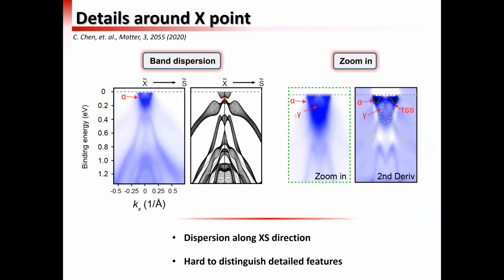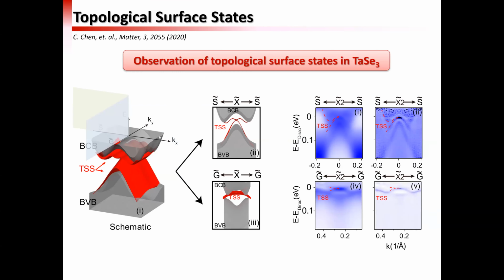If we zoom into that region we just saw before, we were able to see that now, in addition to the blurry bulk conduction and valence bands, there is definitely something in the middle. You can see clearly if we take a derivative of the spectra, and also in this different cutting direction, gamma to X to gamma, there's definitely something in here, and the red broken lines are just a guide to the eye. So there are surface states living inside the bulk gap of the conduction and valence bands of the tantalum triselenide, and so we confirm that this material does have a topological electronic structure in it.